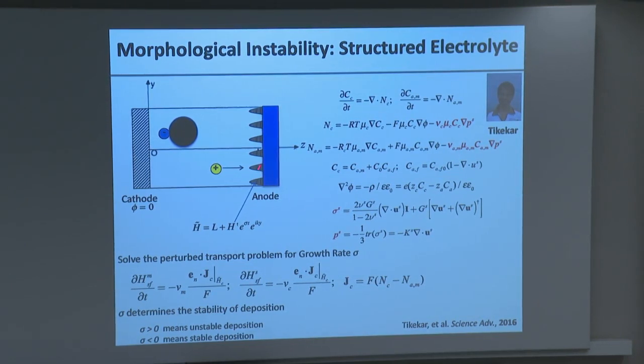So imagine that this is the battery, and this thing is the separator, right? Remember the plastic thing that is between the electrodes. Our thinking was that when a bump forms, it slightly compresses the separator because there's no place for it to go. When it compresses the separator, it basically reduces the volume that is available for fluid, so it increases the pressure slightly on the fluid. And so in the region where the pressure is slightly higher, the chemical potential of the fluid is slightly higher, so the fluid has a tendency to move away from that part to go elsewhere on the electrode. So this so-called pressure migration term actually acts against the bump. If the bump grows, the localized pressure is higher, so you push things out more, so it stops itself from growing. That was just a thought.